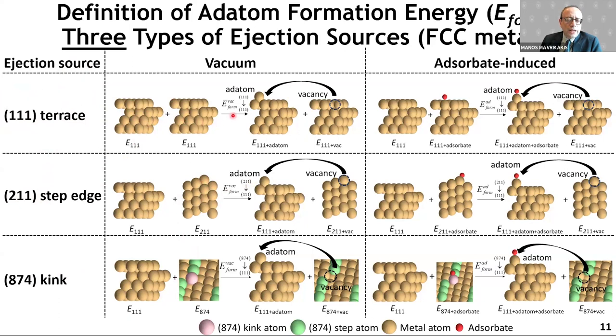So here you start with, say, this kink site. You see this purple colored atom. And then you take this atom and you deposit it in another slab that represents an adjacent facet of 111. So this is the final state. This is the adatom, this is the vacancy. And then you ask the question, what is the reaction energy for this? How difficult, how costly, energetically, is it to eject a kink atom to go there, or a step edge atom, or a terrace atom?